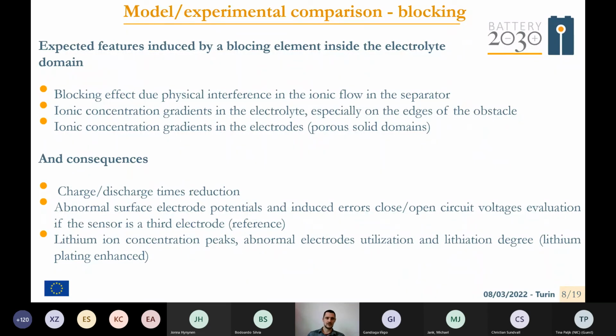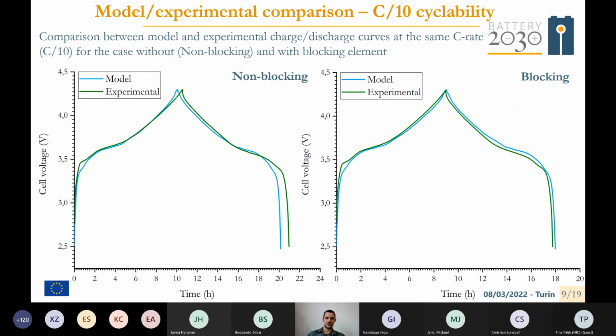These features could drive to consequences, for example, charge-discharge time reduction and alteration, abnormal surface electrode potential, and induced error in closed open circuit voltage evaluation if the sensor is effectively a third electrode. Finally, for example, lithium ion concentration peaks and abnormal electrode utilization and lithiation degree, which may also drive to lithium plating enhanced in some regions of the electrodes.